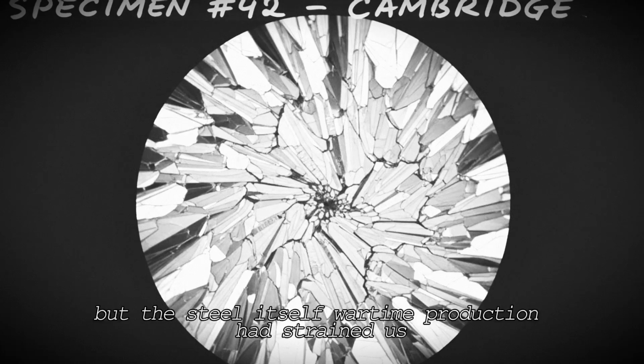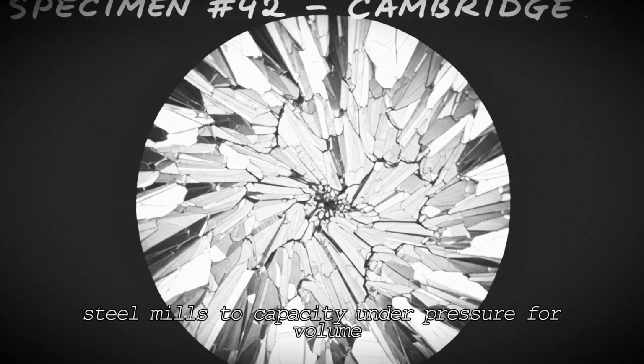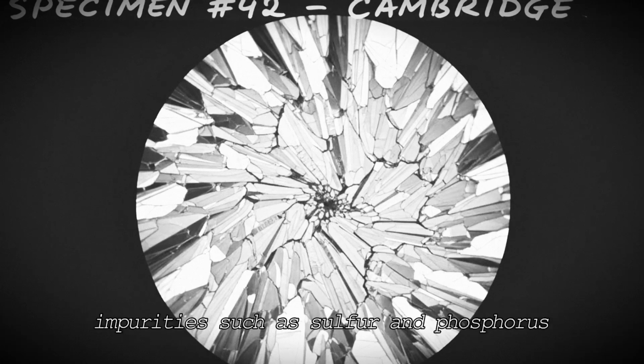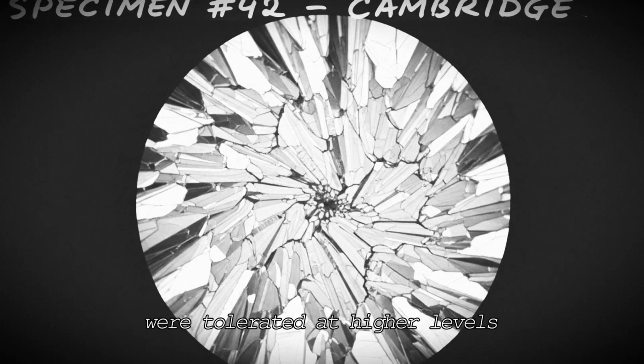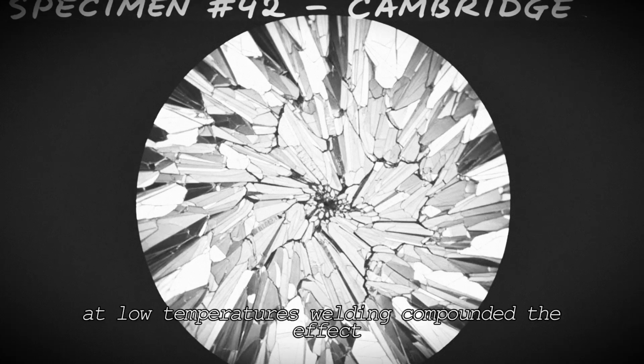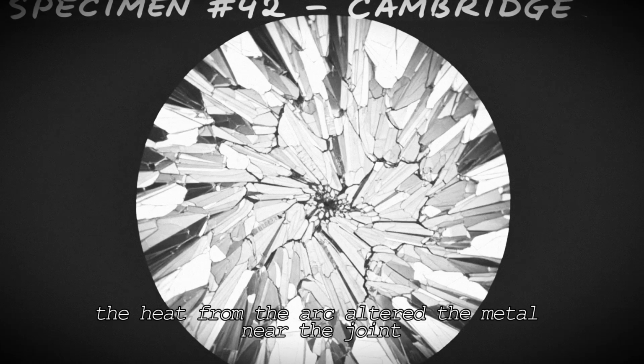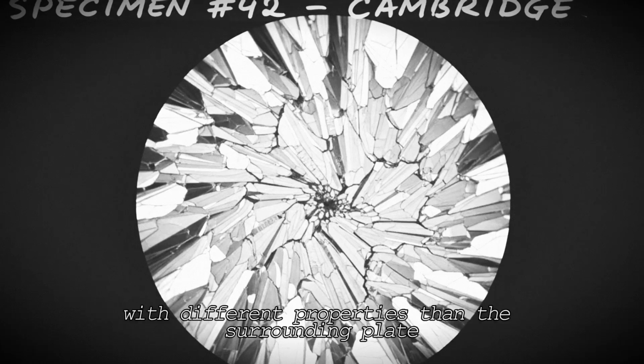Wartime production had strained U.S. steel mills to capacity. Under pressure for volume, impurities such as sulfur and phosphorus were tolerated at higher levels, making the grain structure coarse and reducing its toughness at low temperatures. Welding compounded the effect. The heat from the arc altered the metal near the joint, creating a heat-affected zone with different properties than the surrounding plate.